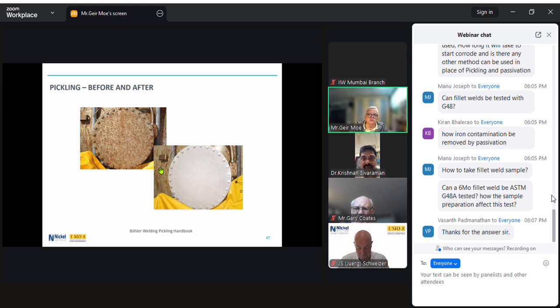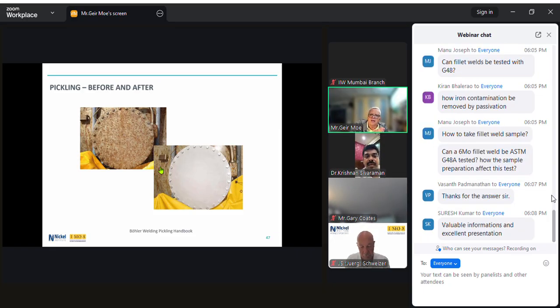I see another one here. Suppose I'm using a grinder to remove heat tint, then a thin layer of passivation is damaged, and how do I recover the chromium layer? Well, the formation of the passive film is spontaneous in the presence of oxygen. So when you damage it, it immediately starts to reform. So there really isn't anything to do, as we saw in the various work by Outokumpu, where they did passivation with nitric and citric acid and hydrogen peroxide, and then just in air. A clean stainless steel surface will form it spontaneously.